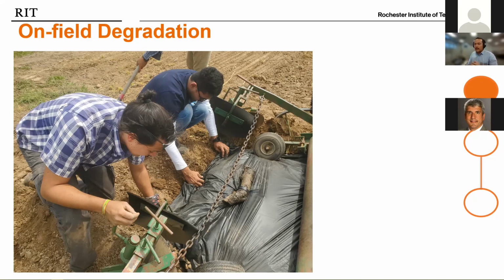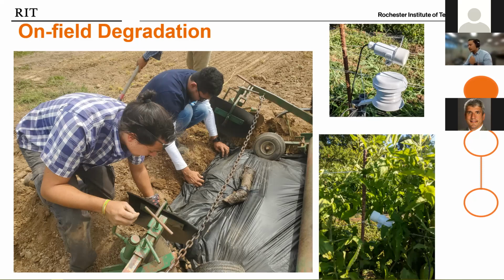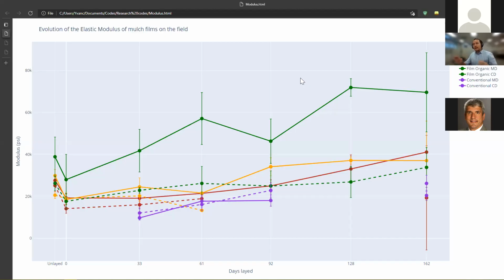So we went there in May and we took samples every month. We also monitored temperature and relative humidity. And what we got, well, we did first some mechanical testing, and that mechanical testing gives us a lot of information. One is the elastic modulus. We can think of the elastic modulus like the stiffness of the plastic. And we see there is a clear trend that it becomes more stiff with time. That is nice in the sense that it corroborates what we've seen in literature, and it's also a continuous measurement that maybe gives us an indicator: the more stiff, the more degraded.